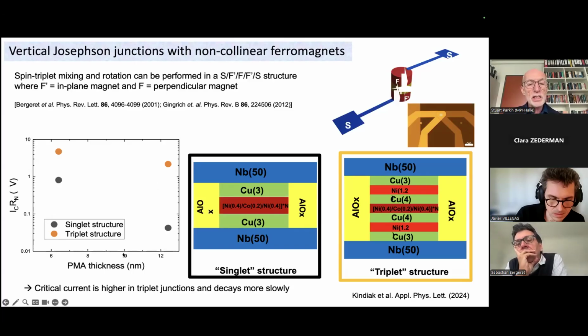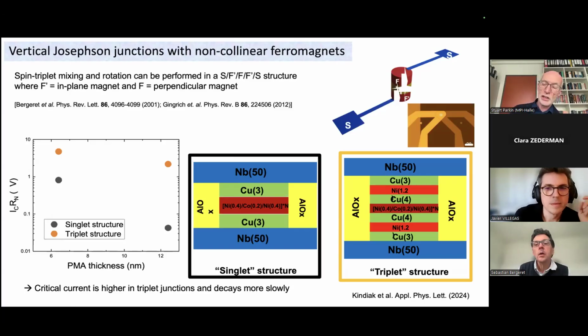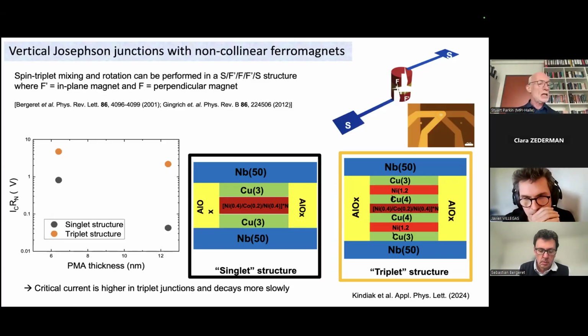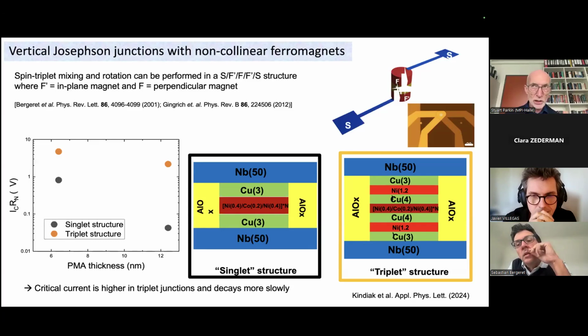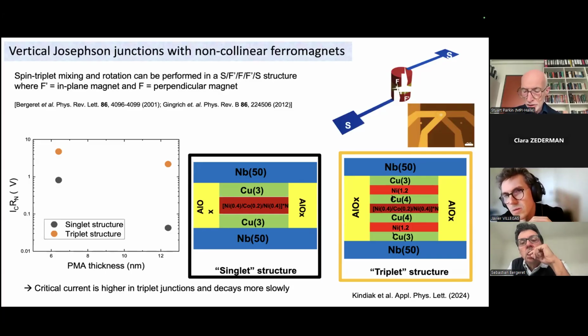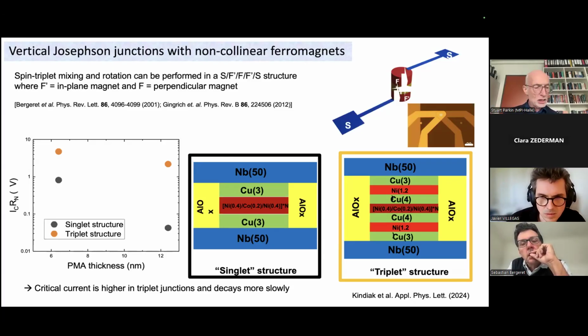And as we increase the thickness again of the middle perpendicularly magnetized layer, the critical current decays much less than for the singlet structure. So the concept here is that the orthogonal orientations of these magnetic layers allow for the generation and propagation of a triplet supercurrent over very long distances. We think it's a very nice experiment, but I have to say, these types of experiments were also carried out by a number of groups prior to us, but this is just confirming this concept that orthogonal magnetizations can generate long-range triplet supercurrents. At least that's the conclusion.